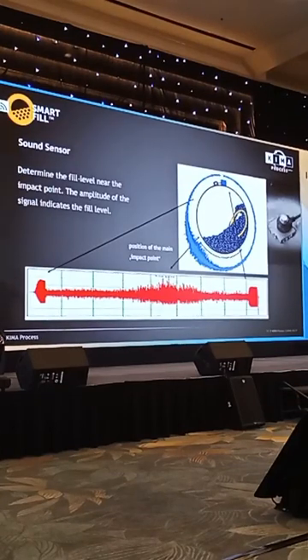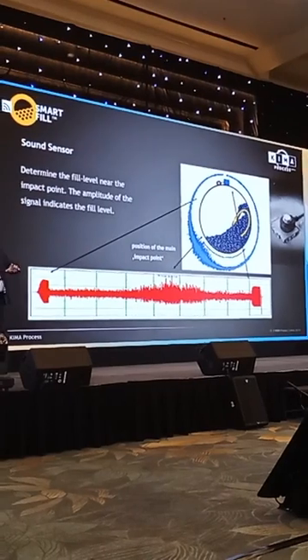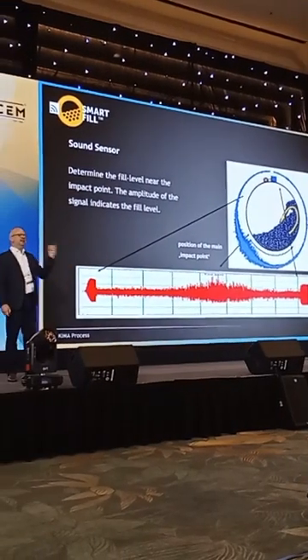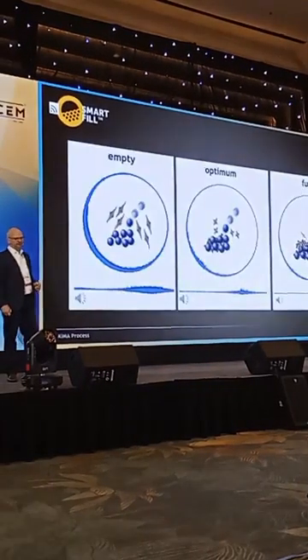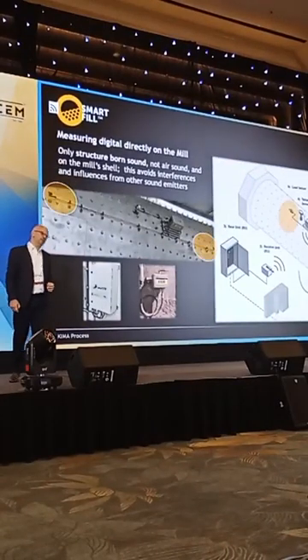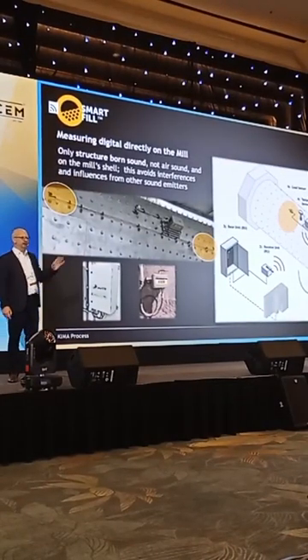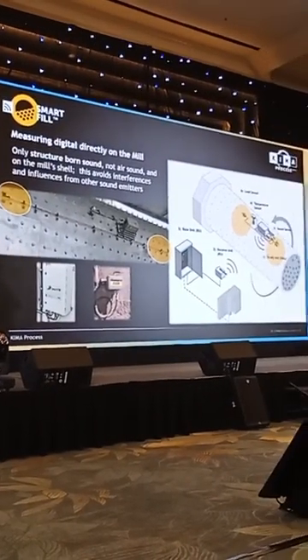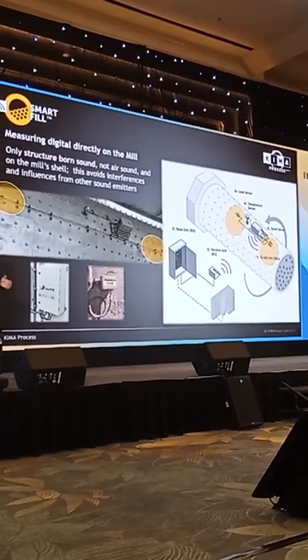Whenever you have wear in your balls, try to imagine that, the flying curve will change. Microphone systems have to be recalibrated usually once per month or once per 3 months. No necessity with this system because it's always getting the main impact point at any pace. I jump a little bit because we don't measure only the precise fill level in chamber 1 and chamber 2, but also the temperature in the diaphragm. And this avoids dehydration of the gypsum in cement mills.